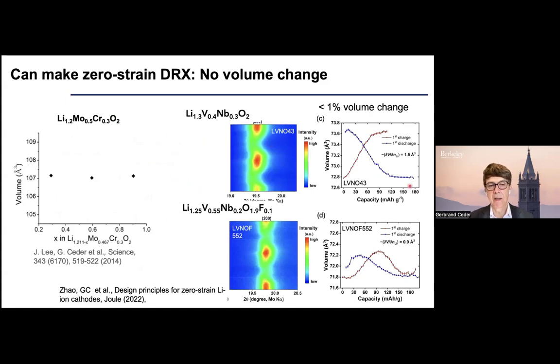There are other interesting things you can do if you go to early transition metals in DRXs. With things like molybdenum and vanadium, you can make extremely low strain and even zero strain DRX materials. The original DRX that we published, the molychromium one, this is the volume of the unit cell as a function of lithium content. As you see, there's virtually no volume change. And both Professor Yabuuchi and ourselves in Japan have shown several vanadium-based DRXs, which have essentially no volume strain at all over a very large capacity range. The volume changes of these materials are 1% or less, and in some cases are even negative. Also, because they are cubic, the volume strain is isotropic, unlike in layered materials.